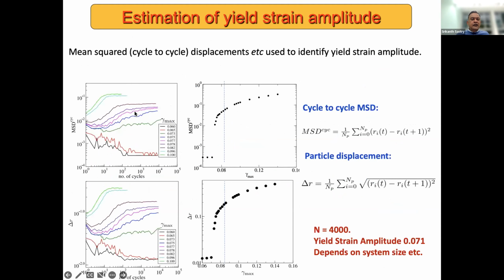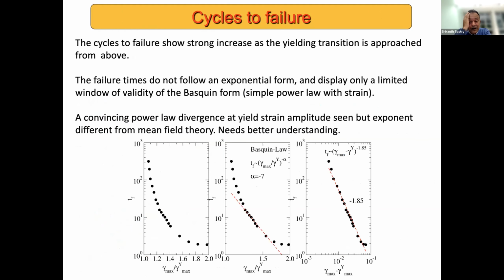I can also look at the amount of displacement of particles from one cycle to the other as a way of identifying where the yielding transition is. I'm not quite sure why, some things have moved around a little bit. These vertical arrow lines are supposed to point to where there's clearly a transition in the behavior, which is the yielding amplitude of 7.1%.